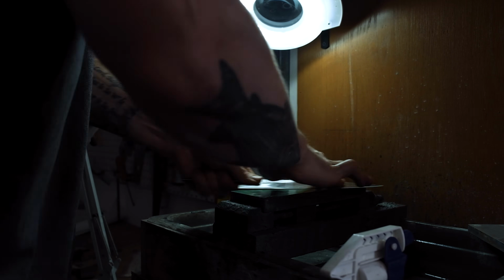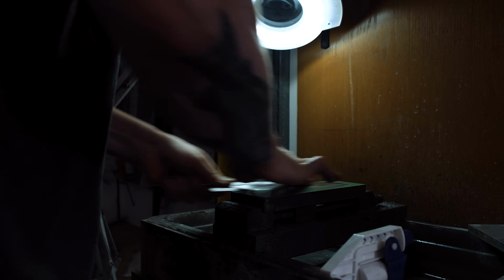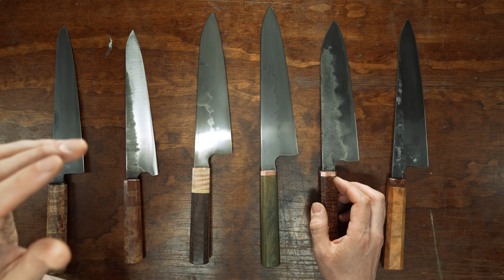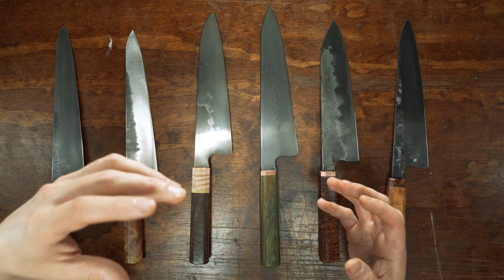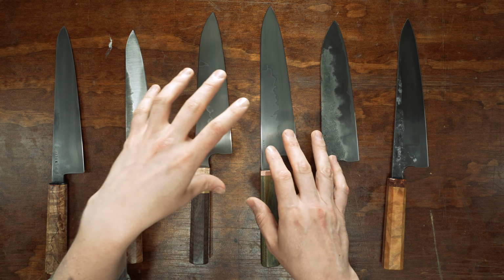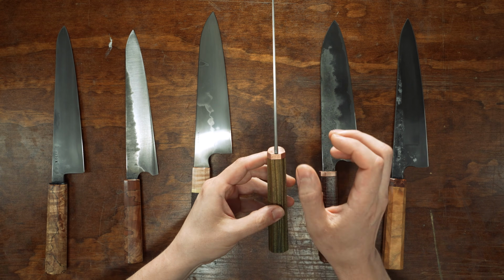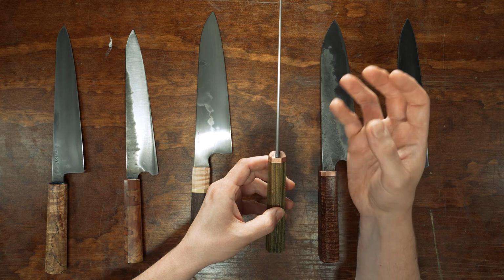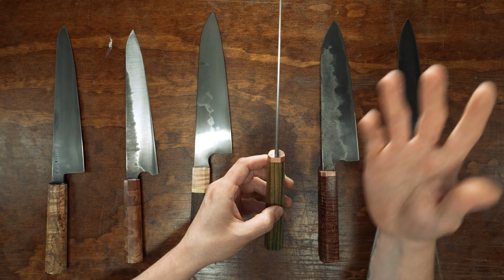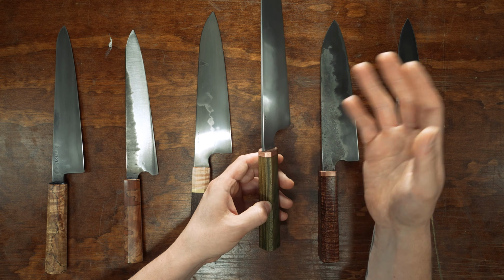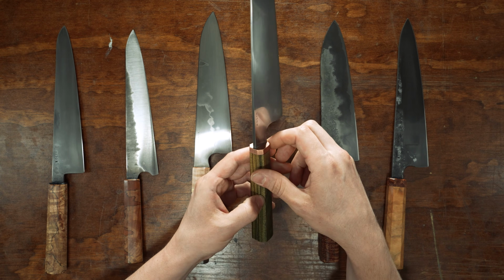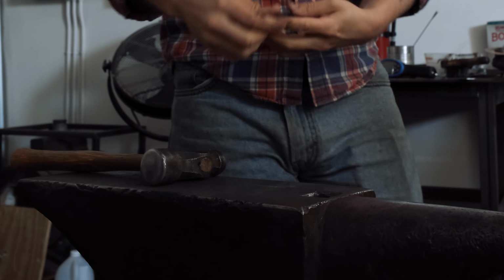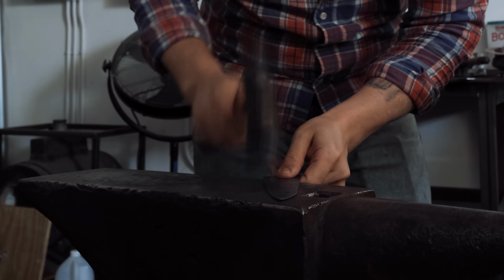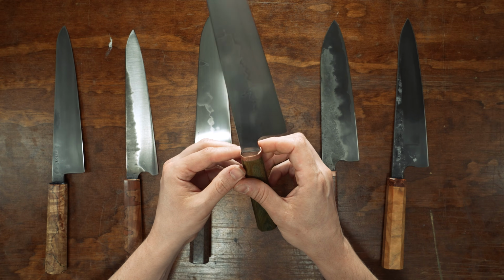One of my main focuses during the forging process is to get as nice a taper in there as possible with a hammer, especially if I'm leaving a forge finish. If I'm doing something where I'm going to completely polish it and remove all the forge scale, like a Honyaki blade, when I forge it, I leave it a little bit chunkier. And then after annealing, so after all the thermal cycles, I will basically shape the knife about 85% of the way, heat treat it, fix any warps if that's necessary, and then polish it up. But even completely clean blades are forged to shape.